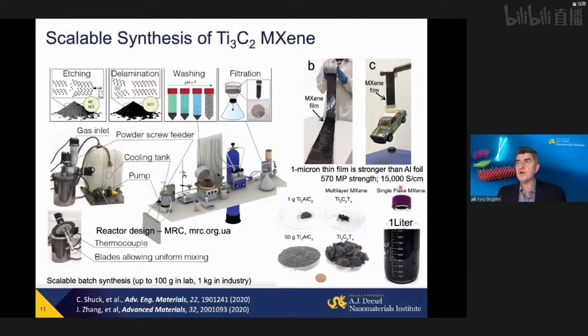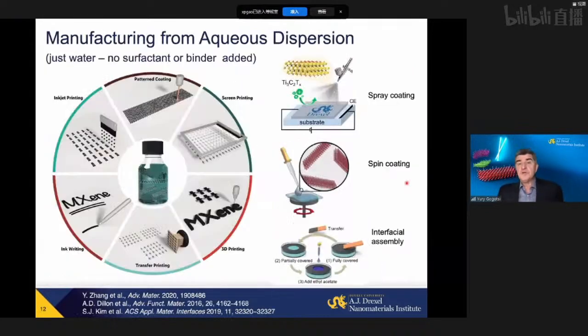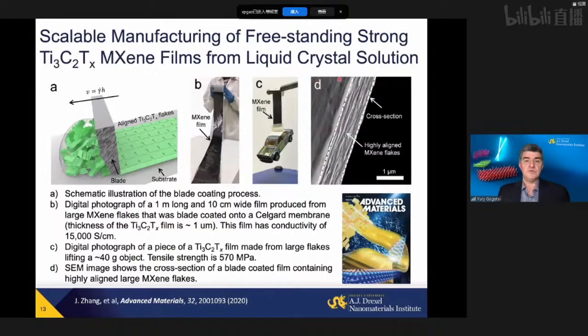And I will talk at the end of my talk a little bit about MXene current collectors that actually suppress growth of lithium, potassium, sodium dendrites. But you can also use any other processing method. You can print them, inkjet print, 3D print, draw with MXene, spin coat, spray coat, pretty much anything you can do with an aqueous colloidal solution, including making this type of film by simple processing. And again, I'm stressing this because, say, if you take graphene oxide, you can process it from water, but then you need to anneal it. You need to reduce it to produce reduced graphene oxide, which is conducting, because GO is not. Here, you don't need anything. You take many other materials.